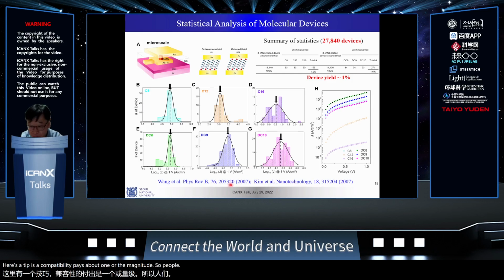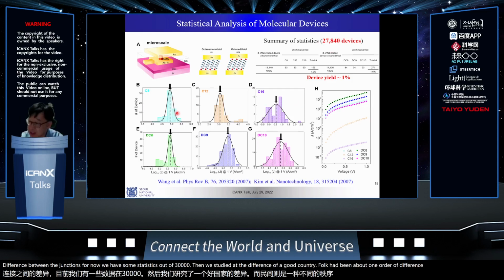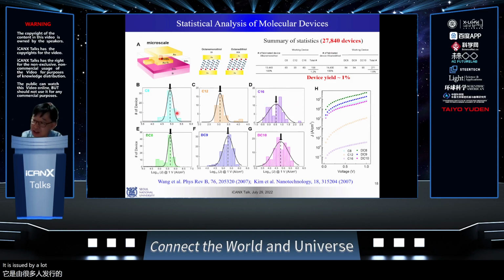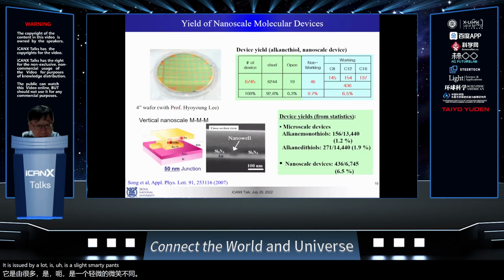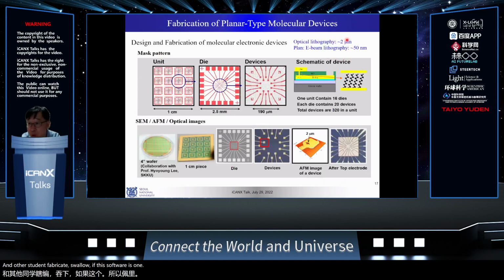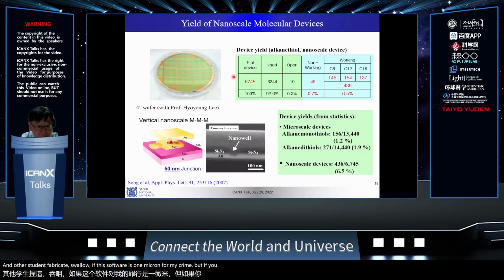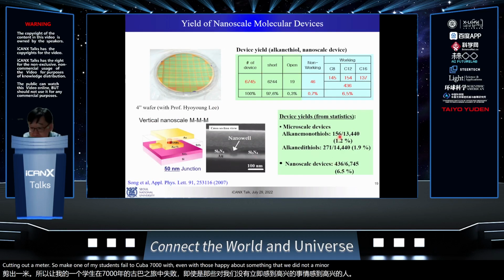So before this, 2007, we didn't know the conductivity difference between the junctions, but now we have some statistics out of 30,000. Then we study that the difference of a good contact and poor contact is about 1 order of magnitude, which is actually not a lot. It's a small difference. And other students fabricate smaller junctions. This so far is 1 micron, 2 micron, but one of my students fabricated 50 nanometer junctions, about 7,000, and even with lithography of a junction of 50 nanometer, the yield is increased from 1% to 6%.